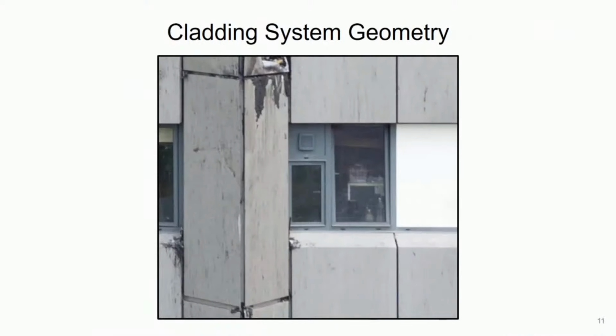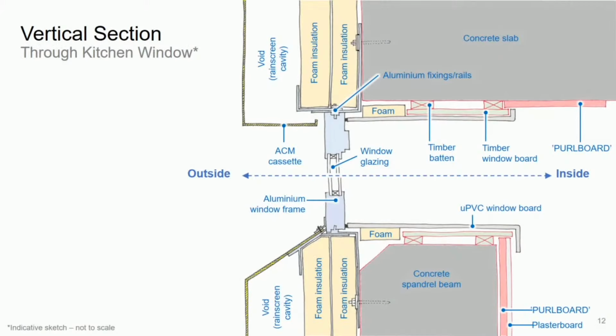I also developed a sketch through this vertical section of the kitchen window of flat 16, highlighting this region of the external wall. The resulting sectional sketch that I developed on this basis is shown here, where the other most likely route of fire spread can be seen essentially like this. This consists of fire exiting the kitchen window or the extract fan panel, which was within the kitchen window, with flames and hot gases impinging on the cladding directly above the window. Again, as the fire enters the cladding, it finds a layer of polymer foam insulation facing a Reynobond PE ACM rain screen with a ventilated cavity between them. At that time, I was unable to definitively say which of these was the dominant route for fire spread to the cladding. My opinion remains that some combination of these two fire spread routes caused the initial ignition that led to sustained burning and escalation of the cladding fire.